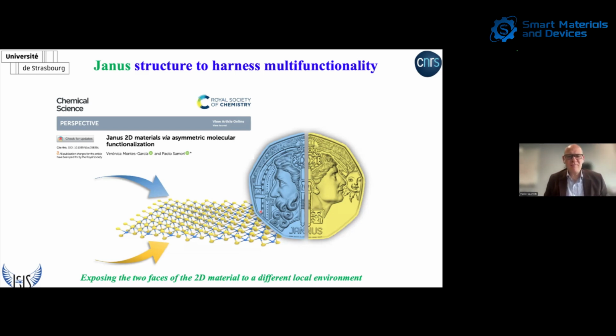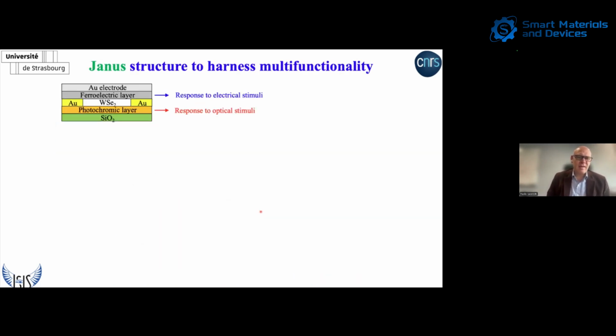And so what are the local environments we can molecularly fabricate? Well, starting again from tungsten diselenide in a transistor, we can expose the bottom surface to a photochromic layer, and here we have already been playing quite enough with this. The top surface is a ferroelectric material, as this allows a dual response to optical and electrical stimuli. Now, photochromic we already discussed, and we will go back to this. For the ferroelectric material, we thought there was no need to invent something totally different.